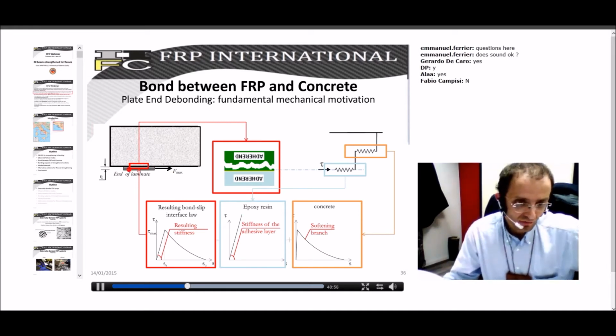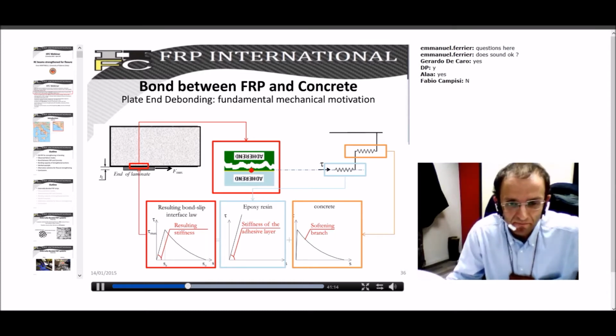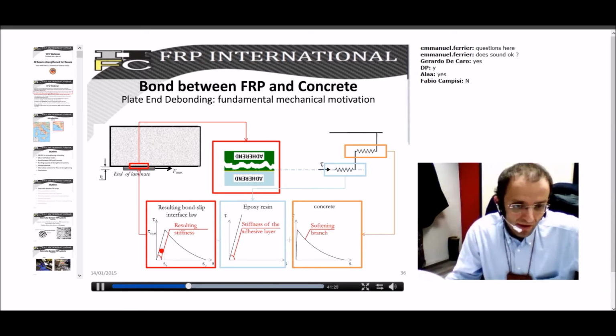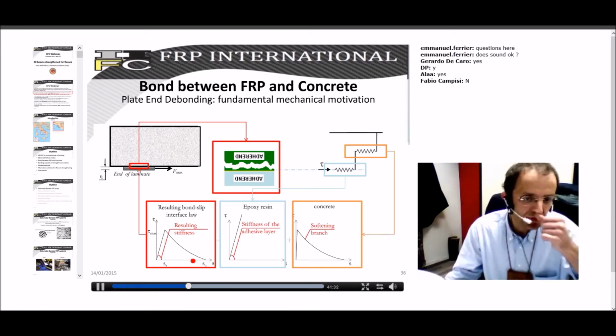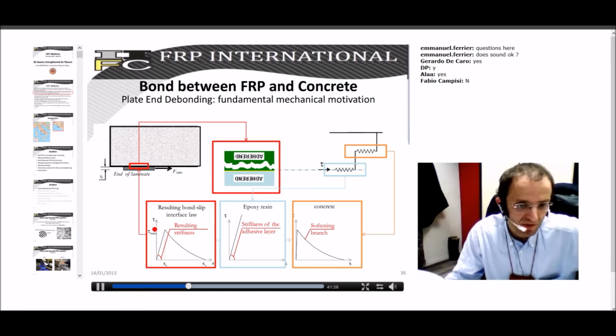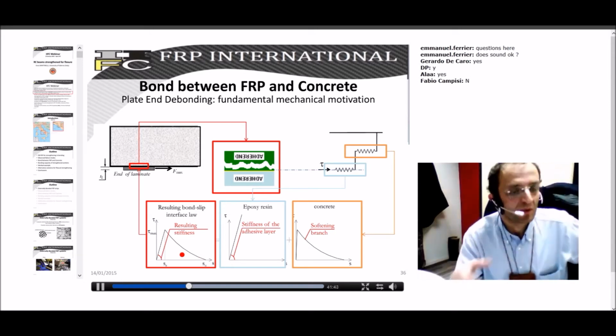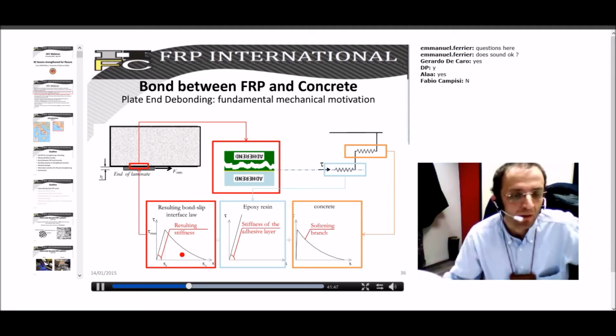If you zoom in on this part, you have the adherend, you have the FRP strip, you have the concrete, which is the more brittle component. This is the adhesive layer. And the resulting behavior of this interface is a series. Basically, it results from a series between the elastic behavior of the adhesive, which can be accepted as elastic, and the elastic softening behavior of concrete. So if you put these two behaviors in series, like it is depicted here, you have probably a tau slip relationship, which is no longer indefinitely elastic, but is elastic up to a certain value of tau, and then you have a softening branch, which can either be modeled as linear or non-linear, or this is just a qualitative graph.